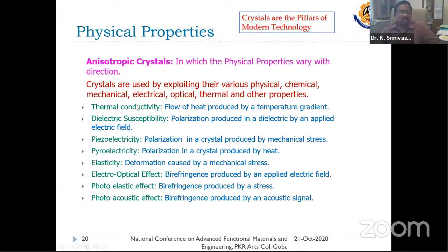Of course, there are several anisotropic properties associated with various crystals. The thermal conductivity, you might have studied, is nothing but the flow of heat produced by a temperature gradient, and dielectric susceptibility is a polarization along a particular direction by the application of an electric field. Piezoelectricity is polarization produced by mechanical stress. In pyroelectricity, most of the IR detectors, the CCTV cameras and arrays we use nowadays, all have pyroelectric properties. So polarization is generated along a particular direction when the heat energy is applied along a particular crystal plane. Then the elasticity, deformation caused by mechanical stress, and the electro-optic effect, photoelastic effect.